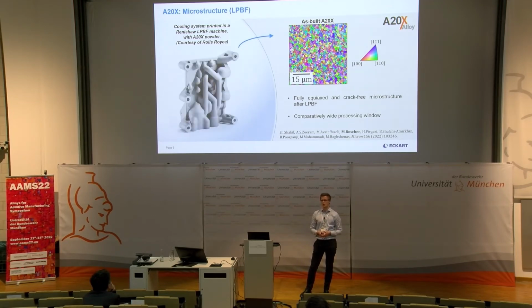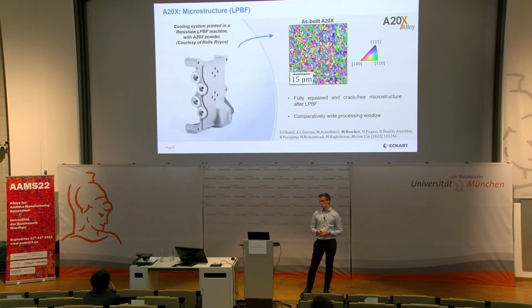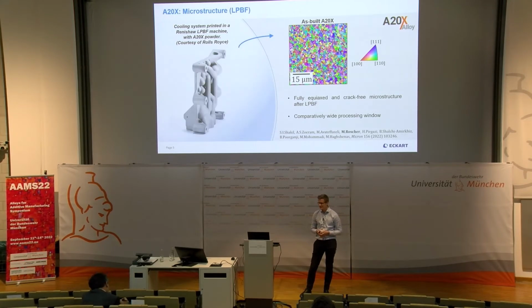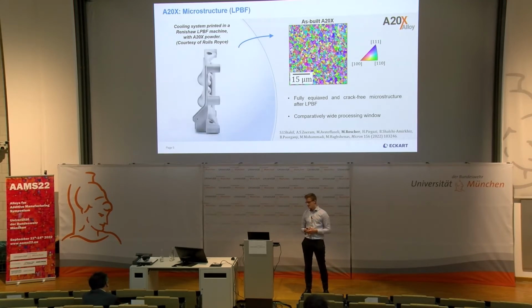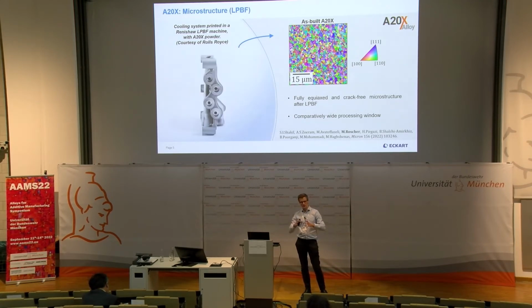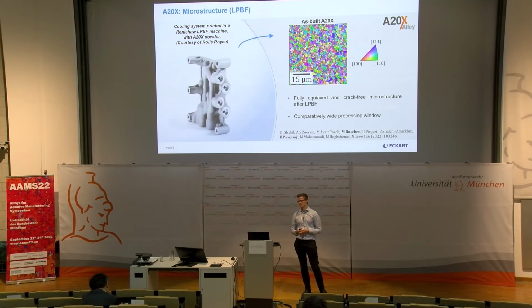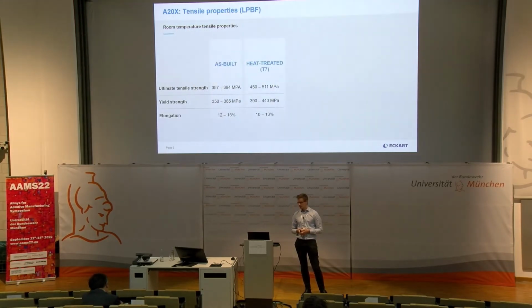What also helps with regards to processability is the fact that A20X does not contain volatile elements such as zinc or magnesium in high concentrations. So the process window is relatively large, a few hundred millimeters per second scanning speed, relatively constant, high relative densities and low surface roughness. So processability is good, but what about tensile strength?